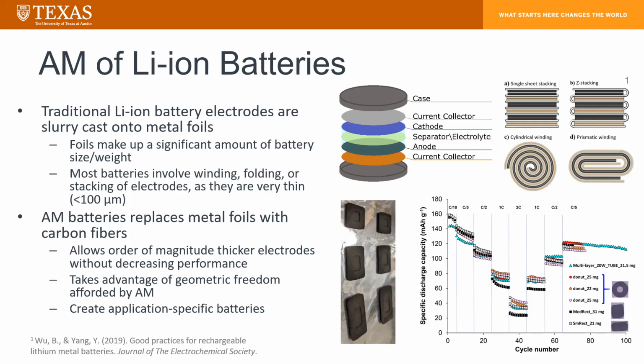So what we've been able to do is remove those current collectors and instead use carbon fibers within our material matrix to build up much thicker electrodes that still have high performance. And when we do this, we're using additive manufacturing to build these, so we can take advantage of the geometric freedom that AM affords us and make conformal battery electrodes. So imagine working on a device, and instead of picking a battery out of a catalog, you can actually design a battery, both the geometry of it and the capacity of it, that meets your specific needs.